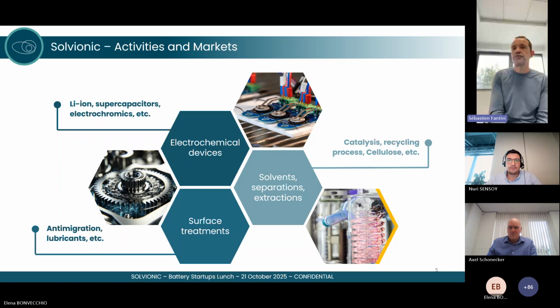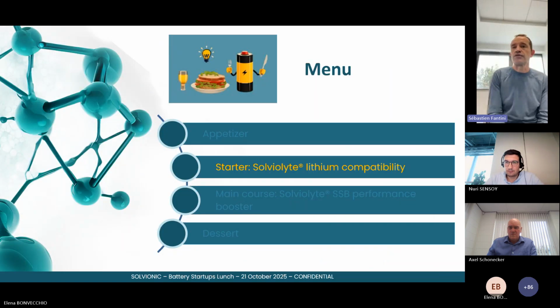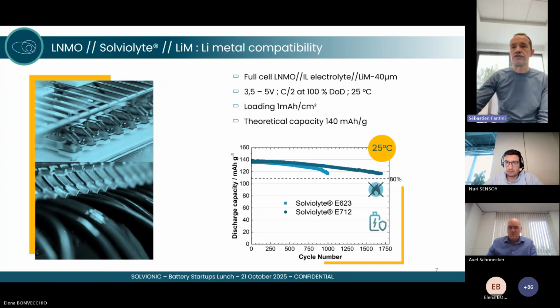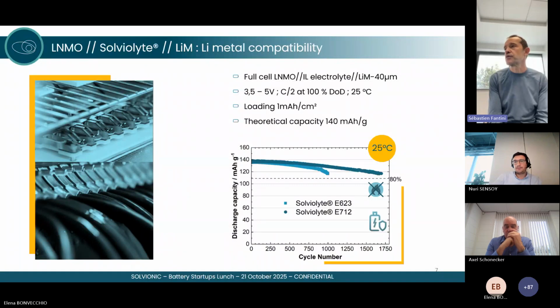Next slide. So now we start with the Solviolyte lithium compatibility. Here you can see a full cell that is mounted with an LNMO cathode, which is provided by a Topsoe company, together with a lithium metal anode, which is provided by another company who produces lithium metal anodes. So you have the cycling condition from 3.5 up to 5 volts, which is quite high voltage.